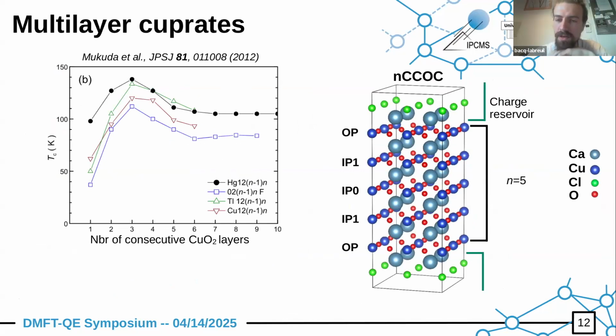No. At present, each plane will be linked to one cluster impurity. And then for each layer, you do it separately, right? Yes, exactly. So the layers see each other at the DFT level and via the hybridization function in some sense, but not directly in the impurity problem. Okay, I got it. So they see each other as a mean field. Yes, but my question is, do you think it is justified to ignore the interlayer correlations? We did some checks for superconductivity, looking for the proximity effect, but the layers would see each other as a mean field.